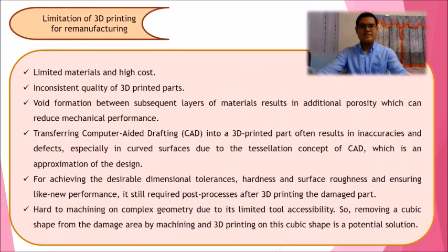Besides, during the manufacturing process, void formation between subsequent layers of material would reduce the interfacial bonding between printed layers. This causes additional porosity in the broken product and reduces mechanical performance.